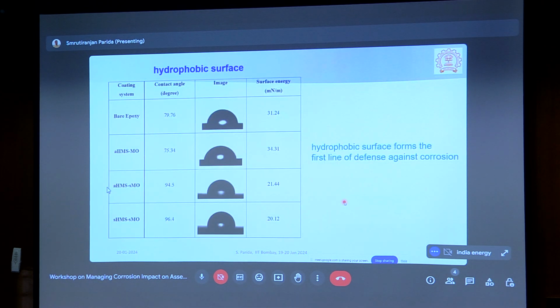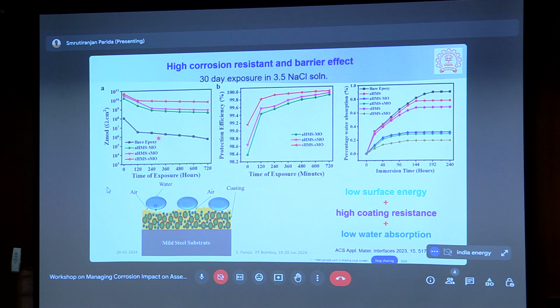Also we have done the corrosion behavior. It's very hydrophobic in nature. At the same time, we have done the long-term exposure study in 3.5% NaCl solution. As you can see here, there is barely any decrease in the coating resistance after long-term 720 hours exposure in NaCl solution. That indicates a very high protection efficiency, and this protection efficiency is also proved from the water absorption test. You can see that this coating has very low water absorption. The combination of low surface energy and high coating resistance also gives you low water absorption.